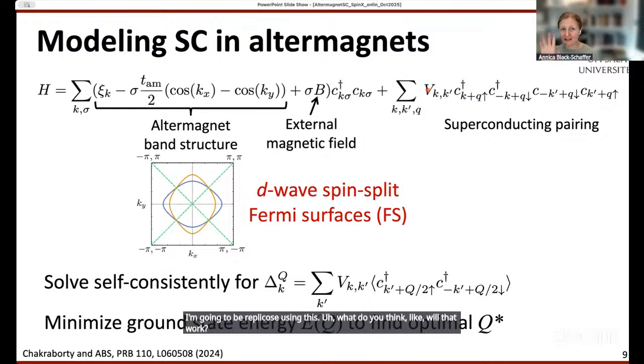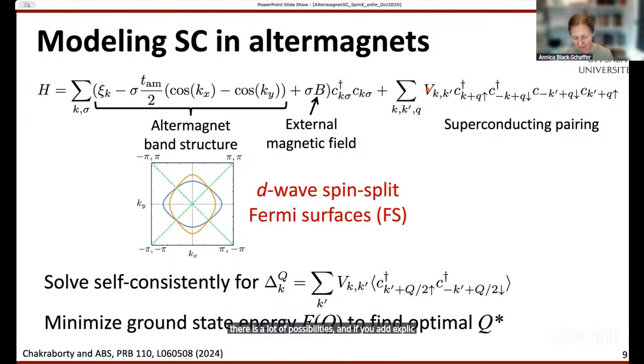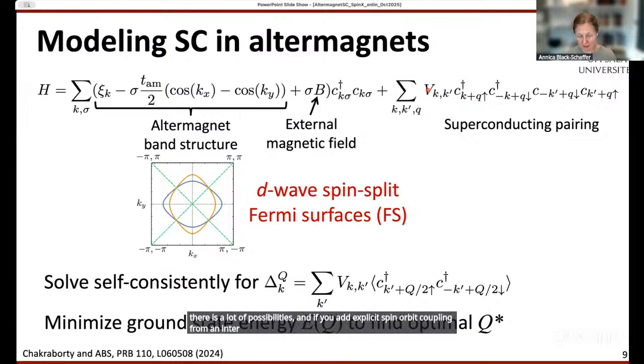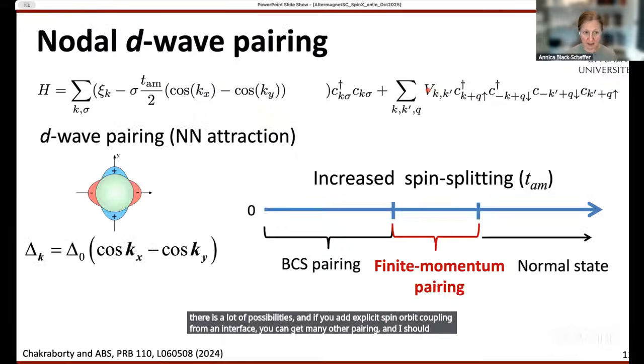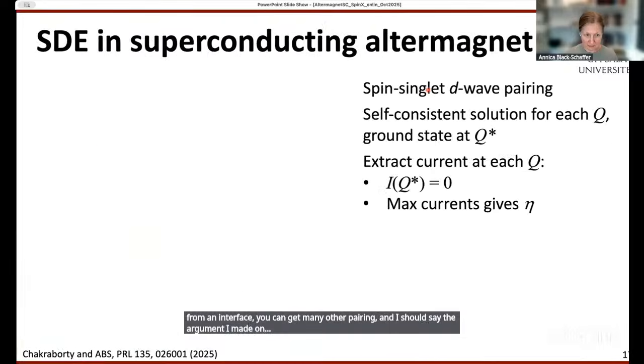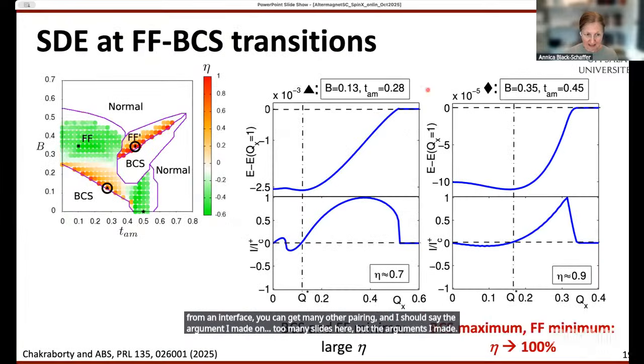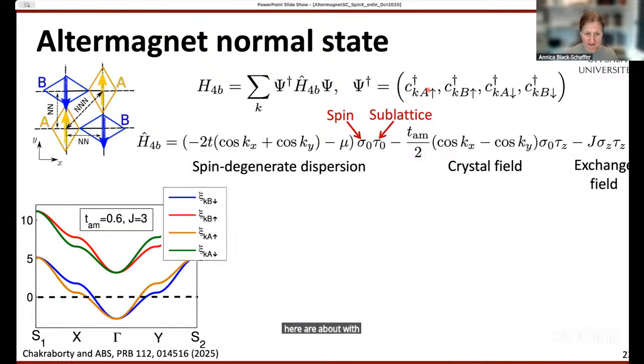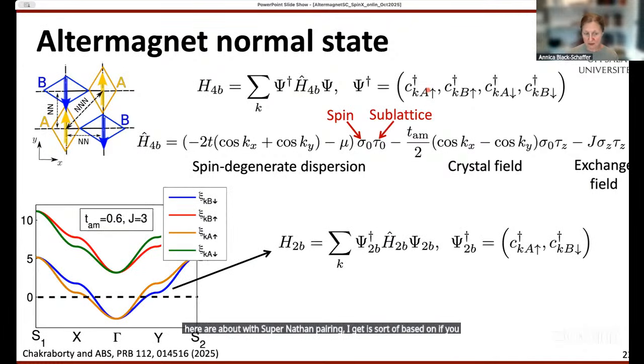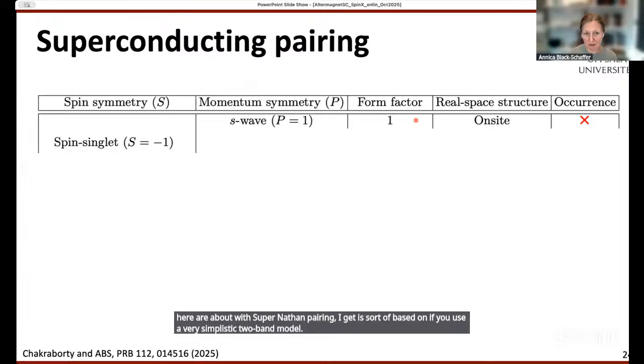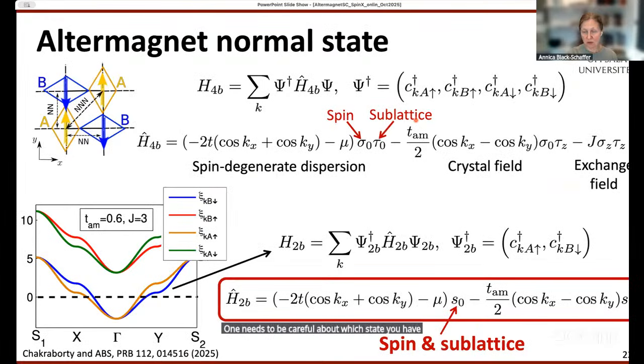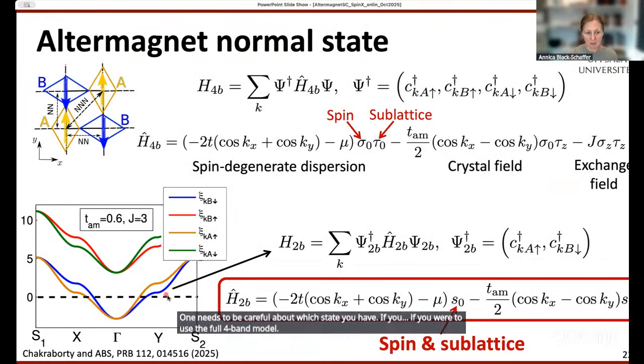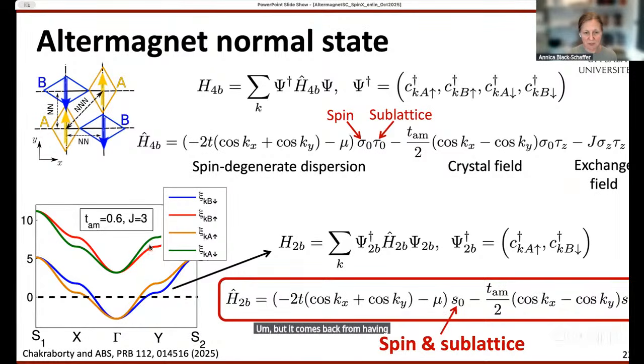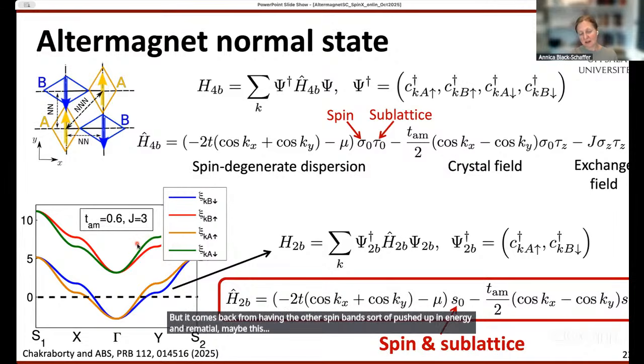There's a lot of possibilities, and if you add explicit spin-orbit coupling from an interface, you can get many other pairings. And I should say the arguments I made here about which superconducting pairing I get are based on a very simplistic two-band model, so one needs to be careful about which state you have. If you were to use the full four-band model, the other spin bands would be pushed up in energy in a real material, and the Fermi level is somewhere else, and so on.